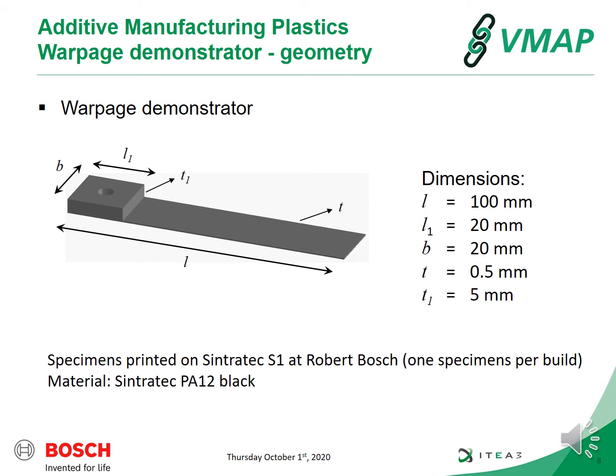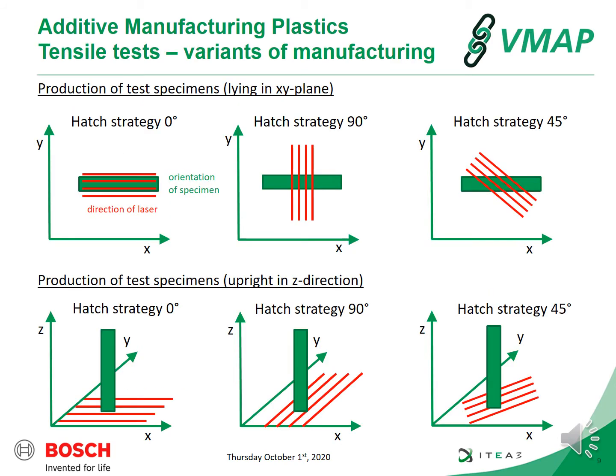Here you can see the warpage demonstrator considered in this project. The warpage specimens were printed on a Sintratec S1 printer at Robert Bosch, considering one specimen per build, and the material used for the printing was a PA12 in black color. This specimen was printed with different hatch strategies, referring to the direction of the laser path. As you can see in the slide, 3 strategies were used for specimens lying in the XY plane, which is the building plane of the building chamber, and the same hatch strategies were used with specimens put upright within the building chamber.